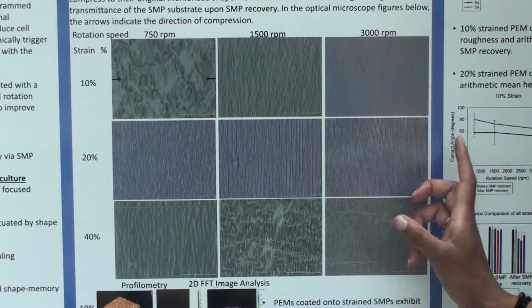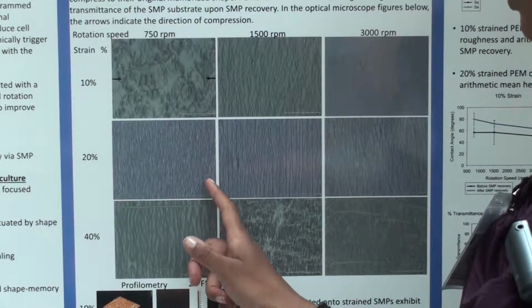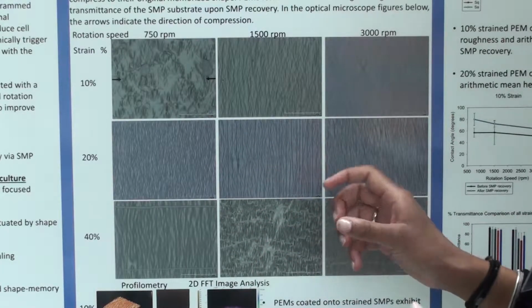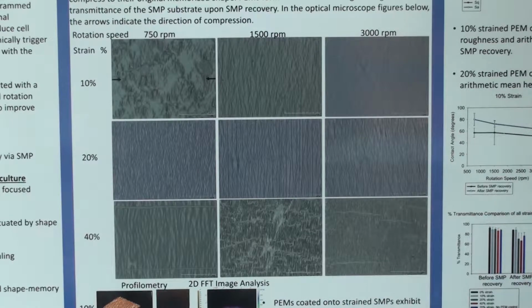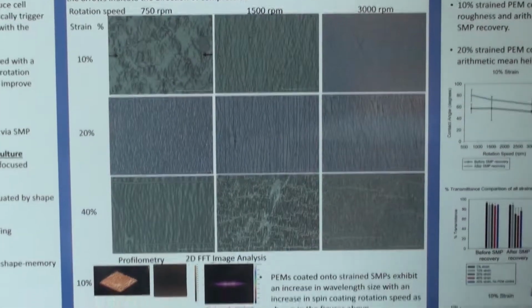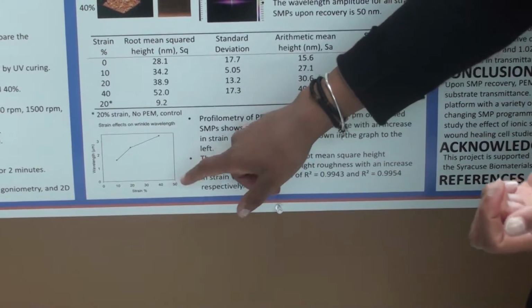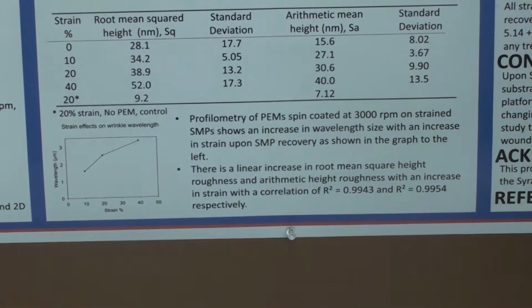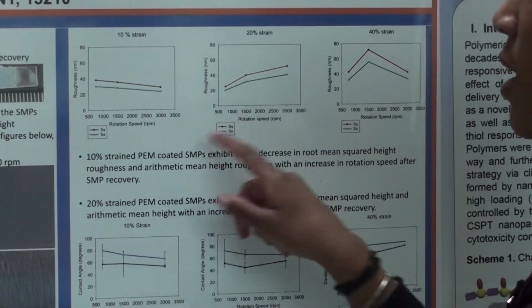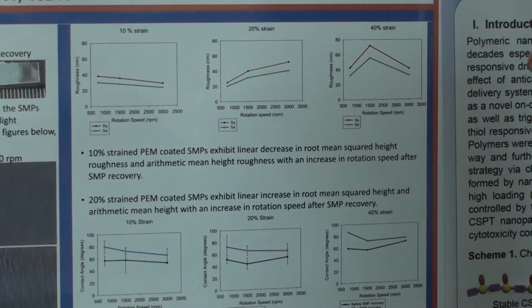And as you can see here, as the polyelectrolyte multilayers become thicker, they have a more dense wrinkle pattern, and there's less space between each wrinkle. And this changes the roughness of the surface and the contact angle, which all affects how the cells will spread onto our substrate. And so what I did was I characterized the wrinkle wavelength, which has a linear increase with the strain that we apply. The wrinkle amplitude is around 50 nanometers, but the wavelength is around 1 to 3 microns. And then we characterized the roughness, which also varies with the strain that we apply and the rotation speed, the contact angle, and the light transmittance.